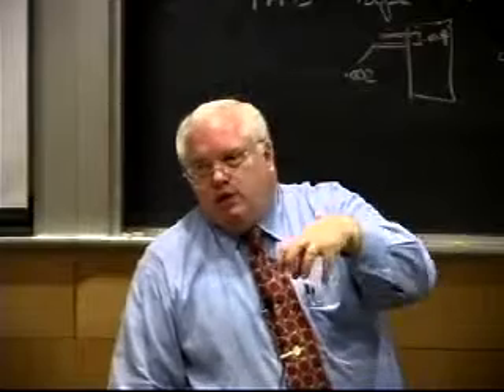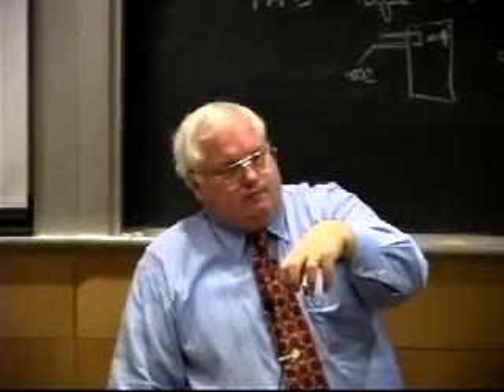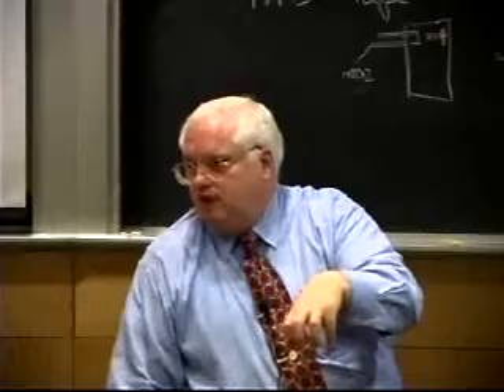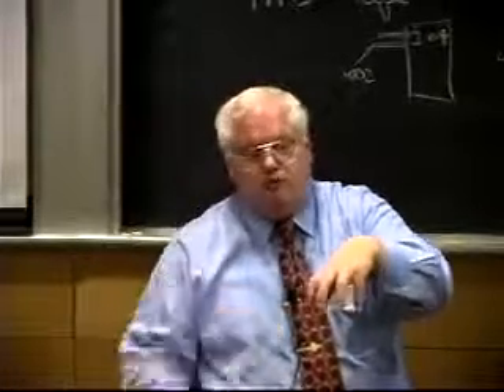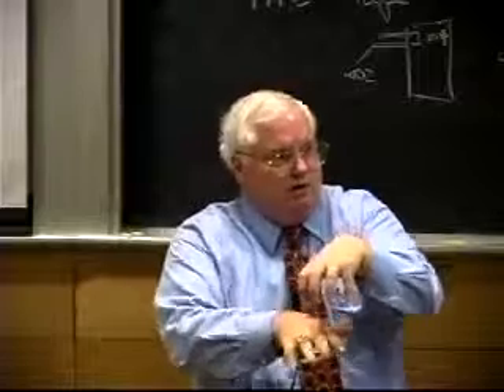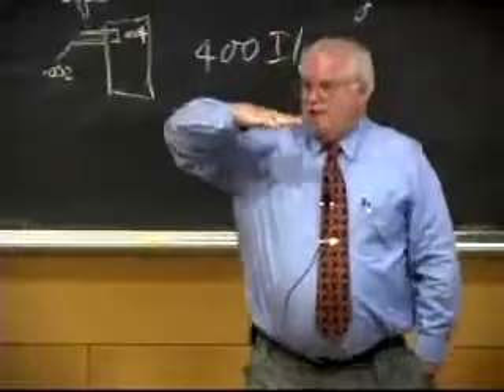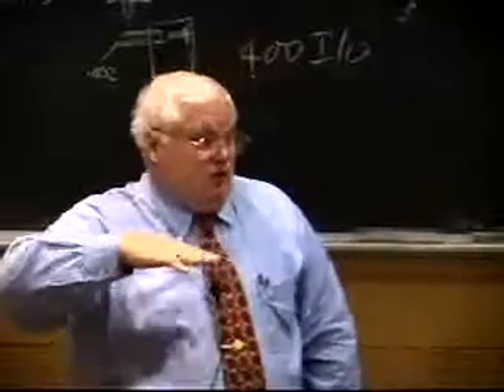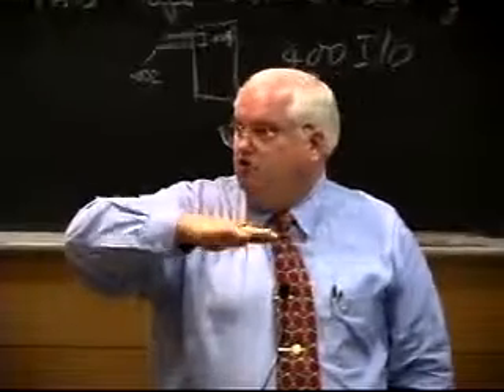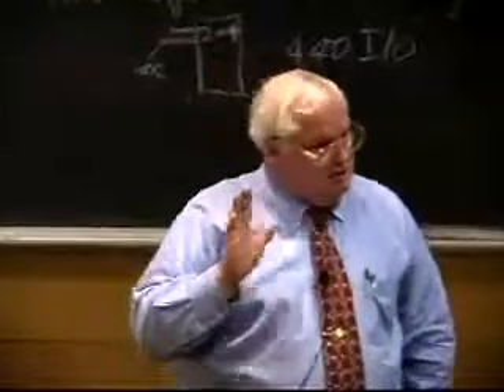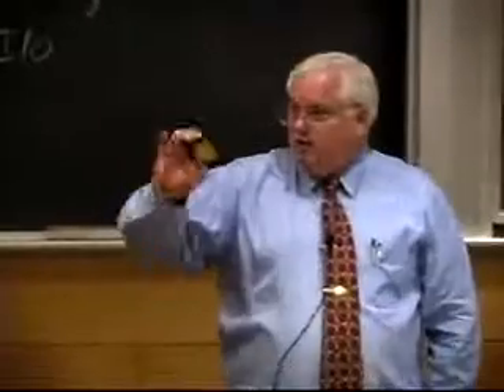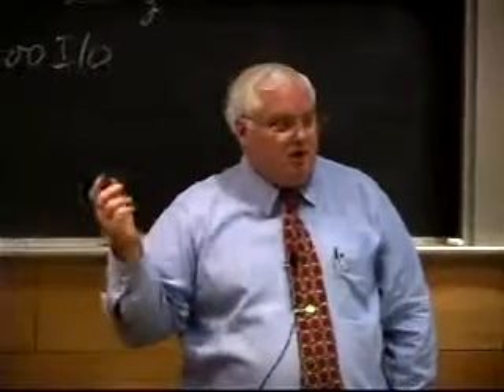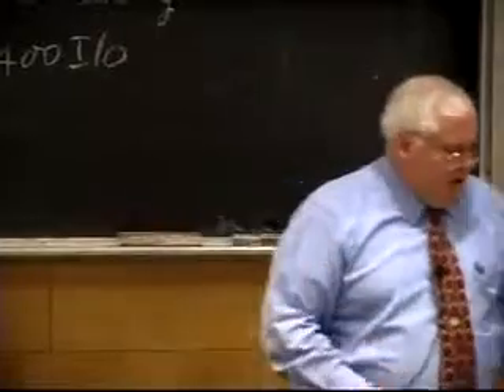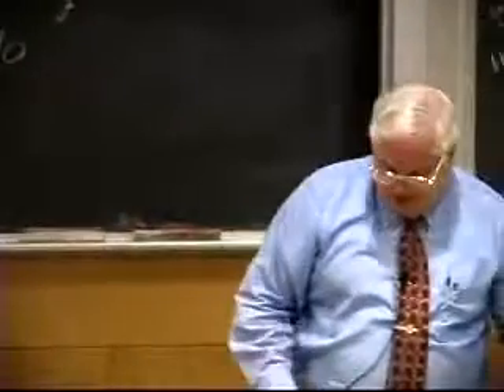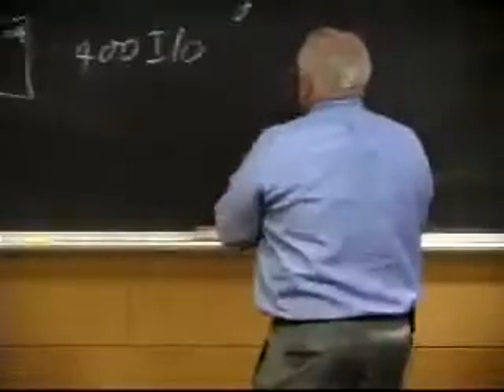Or more commonly, they come down with a square piece of tungsten, and they try to do the whole thing at once. Well, now, if you're doing the whole thing, you have all kinds of alignment problems, because these things may be 2 thousandths wide, but they're only about 1/1000th of an inch thick. So you've got to have this whole thing heated up relatively uniform in temperature, and not have any distortion within a few microns. It's pretty precise, because you get 1 bad bond and you've got a piece of junk that would have been worth a couple $100, right? So it's not easy to repair these. Some of them can be repaired, but it's not easy.